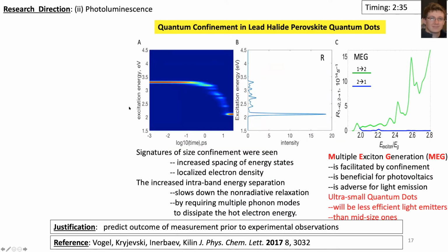And if one brings all these approaches into a so-called rate equation and assesses probability to emit a photon at each stage of time dynamics, one can get time resolved emission, or if one integrates it over time, it will be time integrated emission, which is related to photoluminescent spectrum.